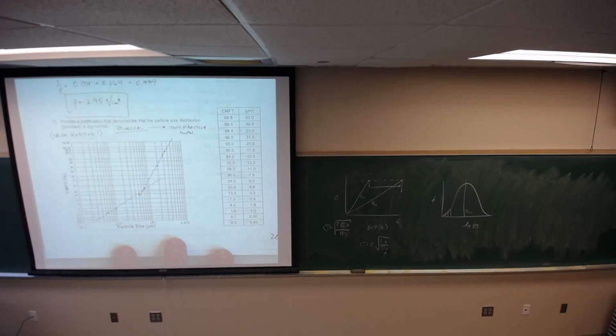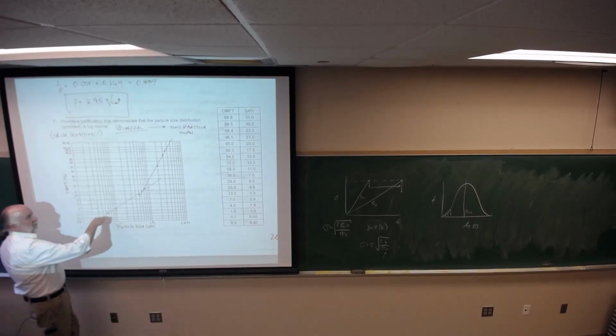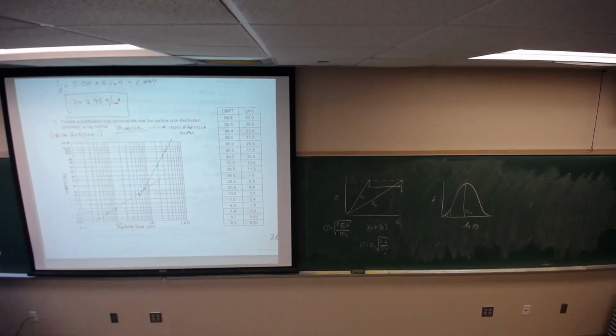Number 7, you have probably room to argue if you feel so inclined. It says provide justification that demonstrates particle size distribution is log normal. In fact, it is not. So you could argue that I misled you. However, I have a question for you all. I would say that roughly half of you fit a curve to this line and told me it was a straight line. Now I have to take some issue with that. If it's a straight line, then you can say it's a straight line. If it's not a straight line, then you have to say it's not a straight line. Just because you want it to be a straight line is not a justification for calling it a straight line. So what you would argue is that you actually had 2 particle types mixed within this sample.